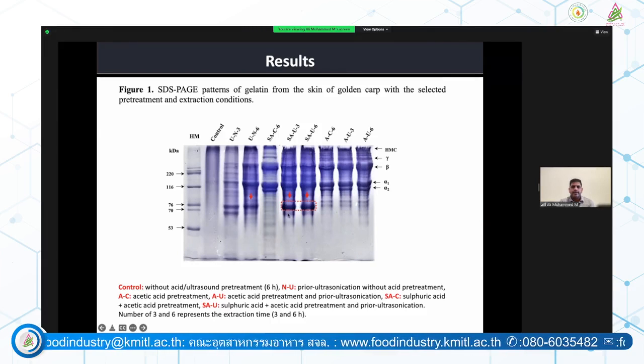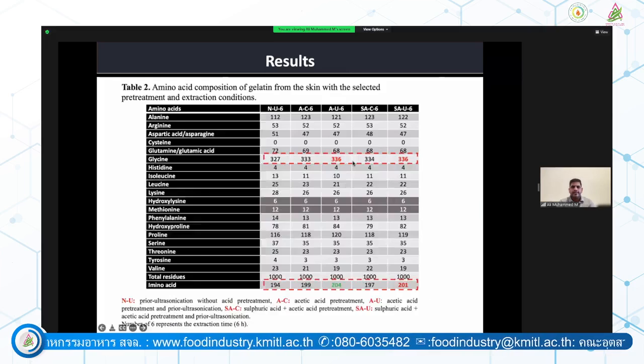And we can see in ultrasound assisted extraction there are lower molecular weight peptides, which can be due to the effect of the strong acid, sulfuric acid, in combination with ultrasound. So at 3 hours and 6 hours, we found a similar effect due to this sulfuric acid. So we found acetic acid is ideal for extraction.